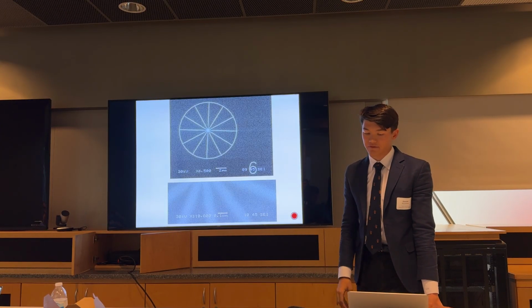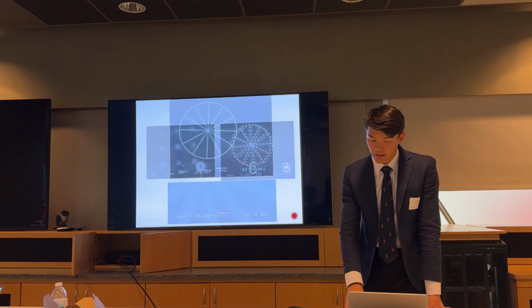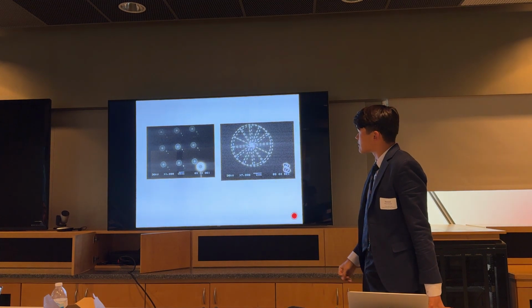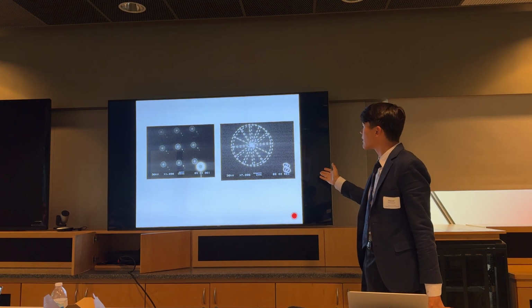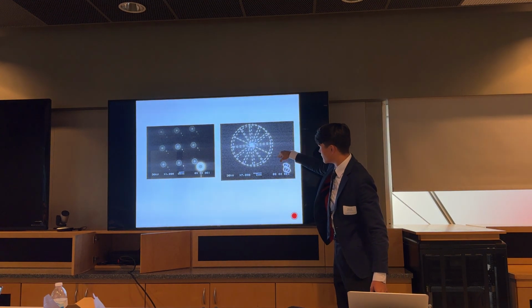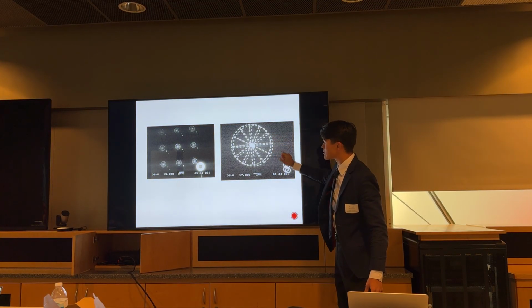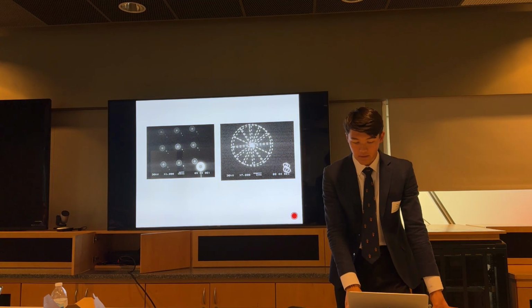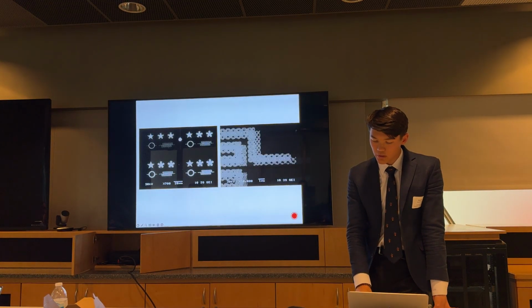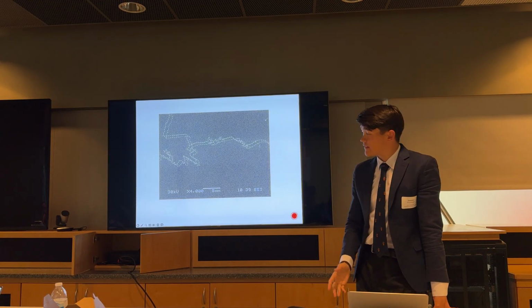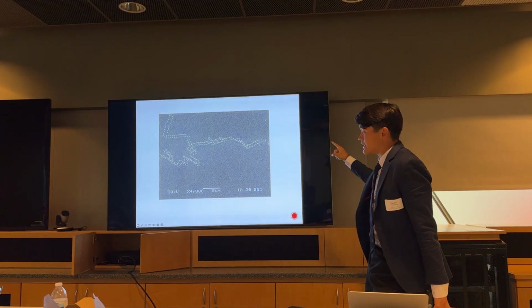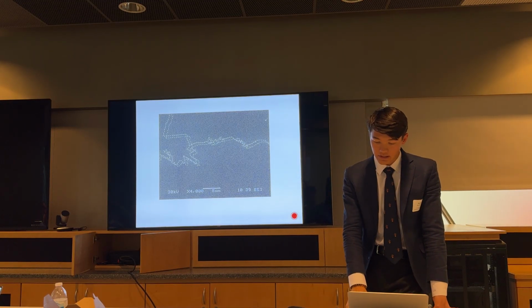Certainly, I didn't achieve this on the first try, and I encountered a problem that looked something like this. So these were what earlier attempts looked like. And you can see that there's this sort of double image with spots all over the place. I tried other patterns as well. Here's a solid region, but you get the same weird noise. Here's a map of the US. These are supposed to be clean border lines, but again, you see the dots.